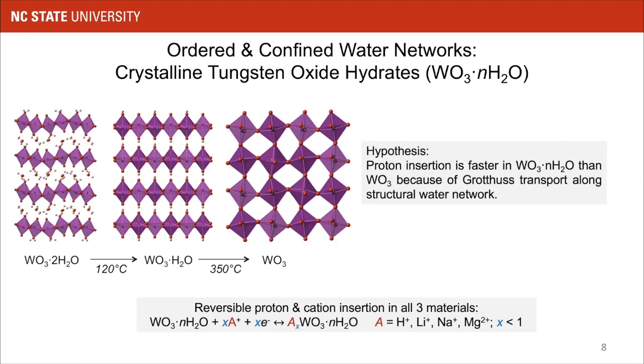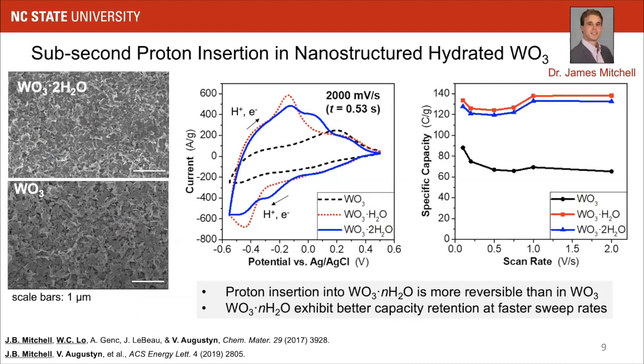And the hypothesis that we came in with for this research was aligned with what was in the literature, which is that proton insertion would be faster in this material because of the Grotthuss transport of protons along the structural water network. This would be perhaps an intuitive approach to thinking where the protons would go. And that's why we would observe fast proton insertion kinetics electrochemically. So this is work that really underpinned the dissertation research of James Mitchell.